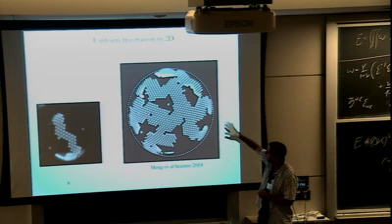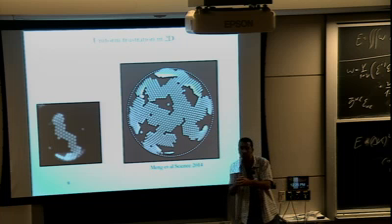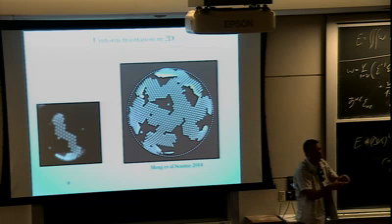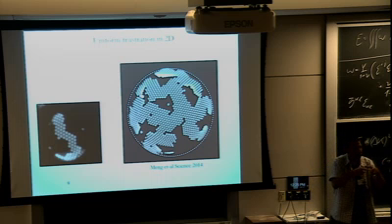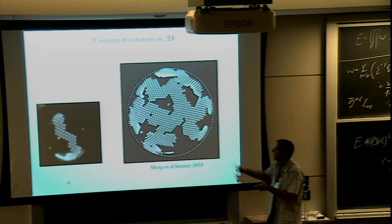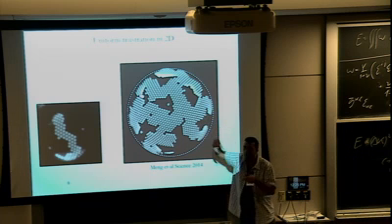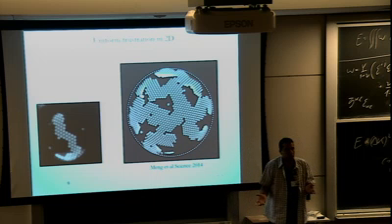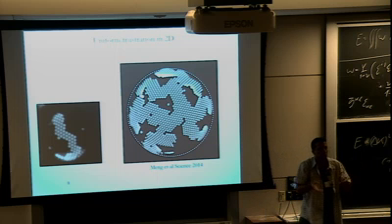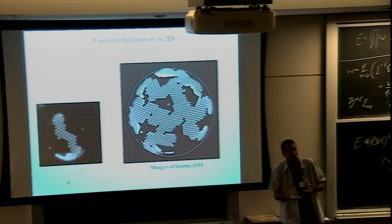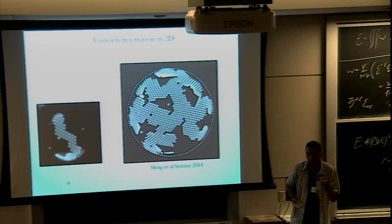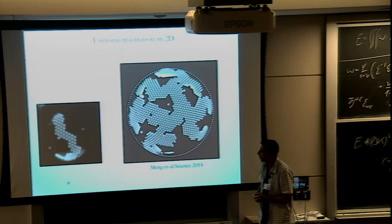And I didn't include this in, but you see that when they nucleate, they make very small isotropic patches, and then they reach a typical width. And then they make these ribbons of a relatively constant width. And now they meander and go around because no one told them they had to be straight, but they make filaments of a certain width. And that is given by the geometric length scale.